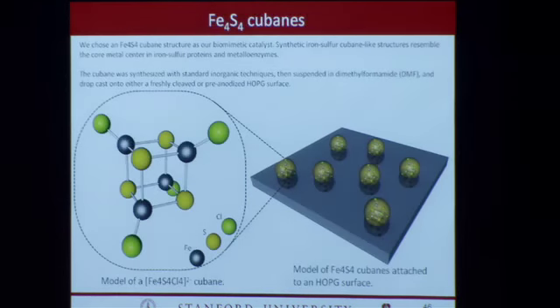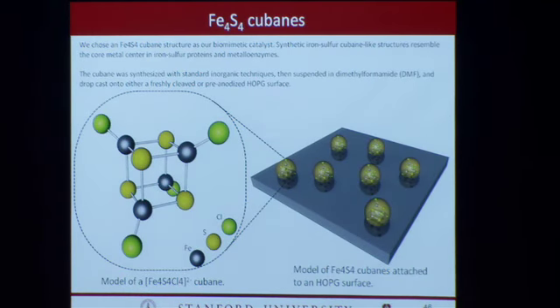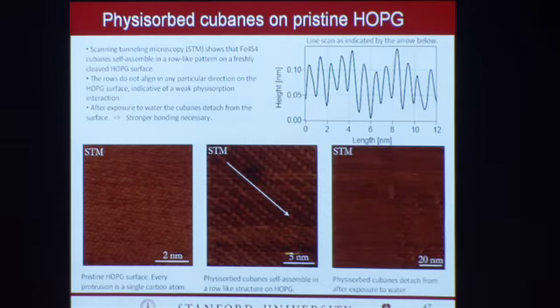And so this is work that we did in collaboration with Ed Solomon in the Department of Chemistry, because we were going to set out to synthesize these types of mimics that were similar to the carbon monoxide dehydrogenase enzyme. But it turns out that when we were looking at the paper, Ed Solomon does a lot of spectroscopic work on these, and so he was very kind to loan us some of these materials. And so the question really became, how can we support these onto an electrode surface to pump them with electrons to ultimately reduce CO2?